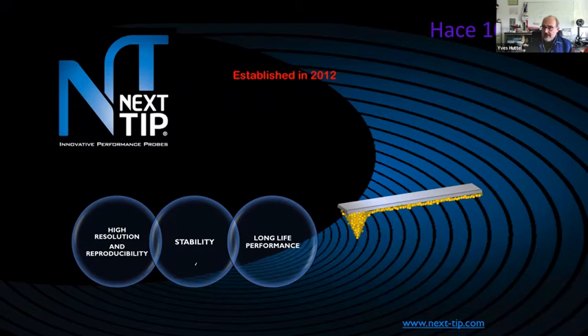But surprisingly, the customers of Nextip were much more interested in the stability of the tips than the resolution. Because as you have this coating, there are many, many nanoparticles. If your tip gets contaminated by a molecule, for example, and you are working with a silicon tip, you have to remove the silicon tip and put another one. So you have to start again the measurements. But in the case of this coating, you can press the tip on the surface, remove the molecule, and you will still have a nanoparticle that will allow you to continue measuring, which is very, very convenient. So this is just something that you work for an application thinking that the customers will like a special aspect of your tips, and at the end of the day, they prefer another one. But it's amazing.